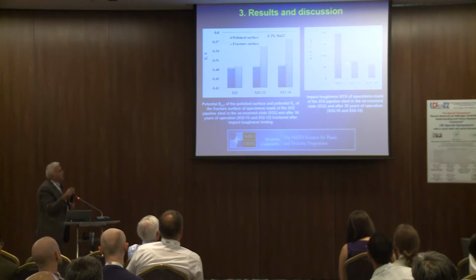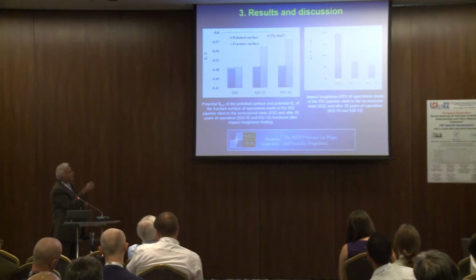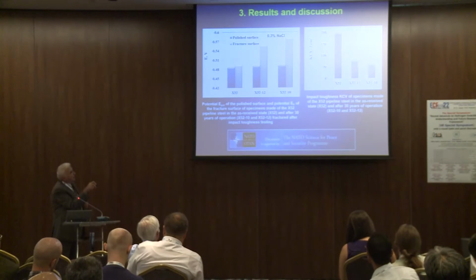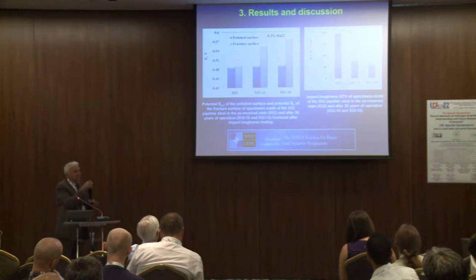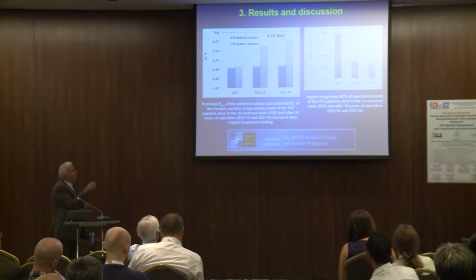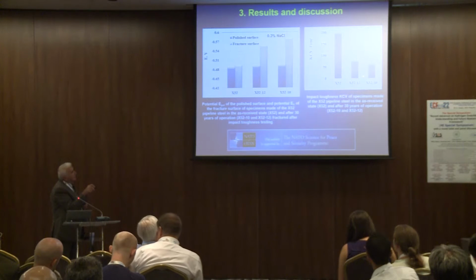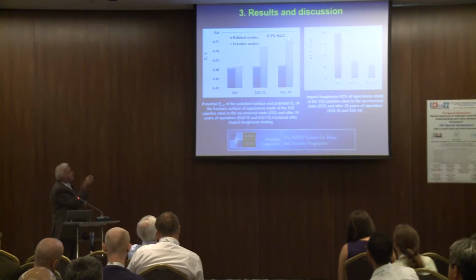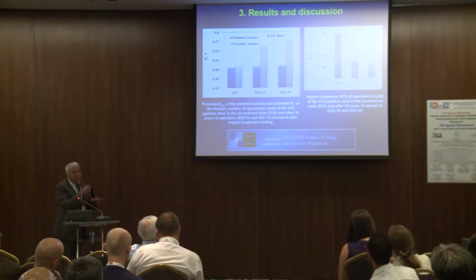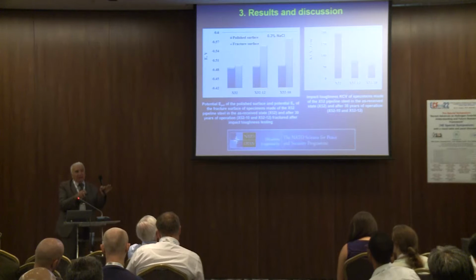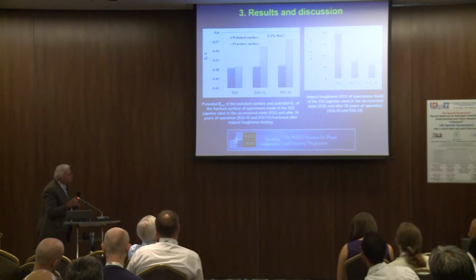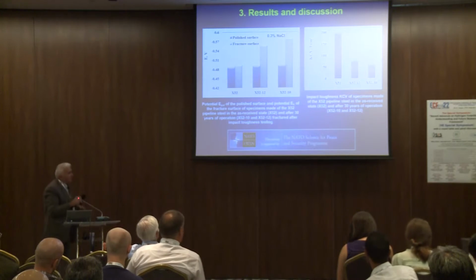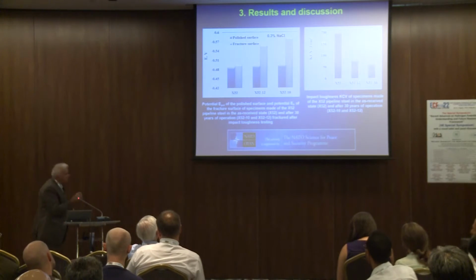On the right figure, you can see the impact strength for such states of materials. High level for the as-received state, and low level, approximately 3 times lower, for exploited metal. For more degraded metal, we obtain more difference between the potential for polished metal and the potential on the fracture surface.